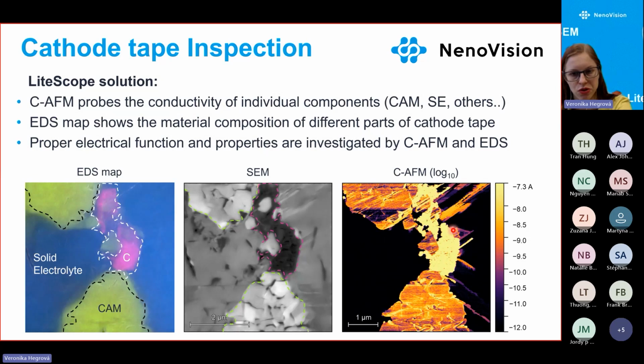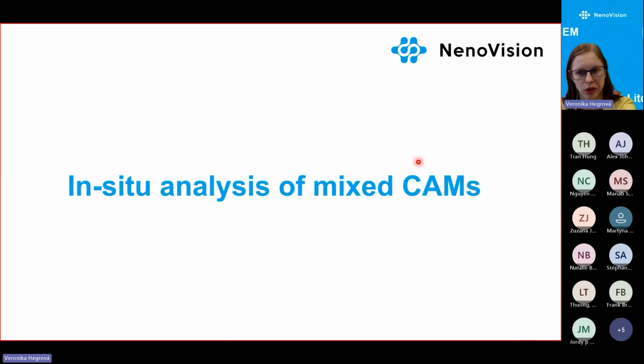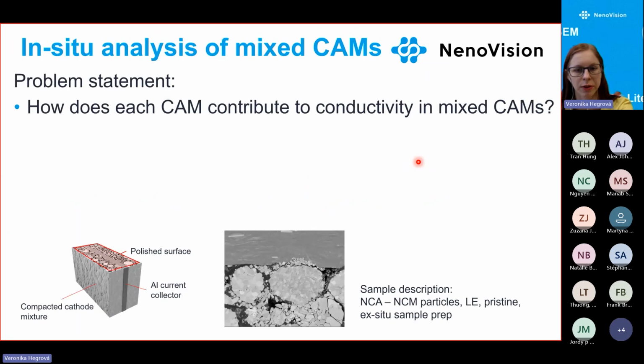and carbon, which is strongly conductive, which confirms that the carbon is added there as an additive to make the interparticle connection better. So even when there are cracks propagating, the carbon helps with the conductivity, the current flowing further. This was analyzed using conductive AFM, SEM, and the EDS together.